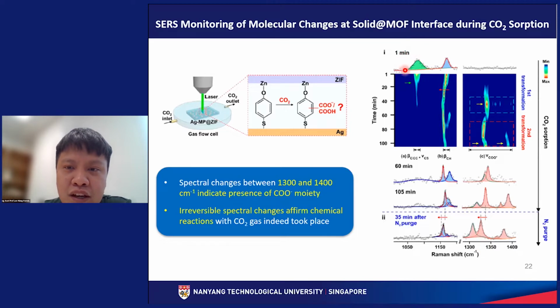Right now the two peaks over here are the characteristic peaks of our mercaptophenol. What is more interesting is between the range of 1,300 and 1,400. So in this region, we expect the carboxylate vibrational mode to be present. As we flow carbon dioxide through our system, we can observe an evolution of a set of peaks very close to time equal to 60 minutes. Subsequently, as we flow more carbon dioxide, we see that these two peaks slowly evolve into 4 additional peaks, or rather form 4 new peaks.